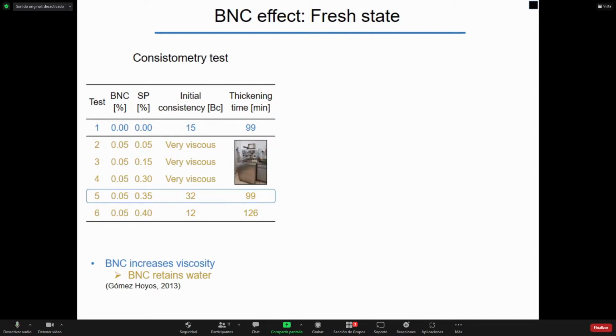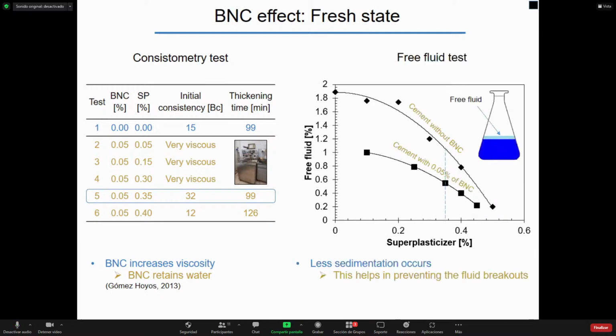In this case, we determined the initial consistency and thickening time of the reference sample, and we tried to emulate this with samples with bacterial nanocellulose. In this case, we needed 0.35% of superplasticizer in order to have a similar viscosity to the reference sample.